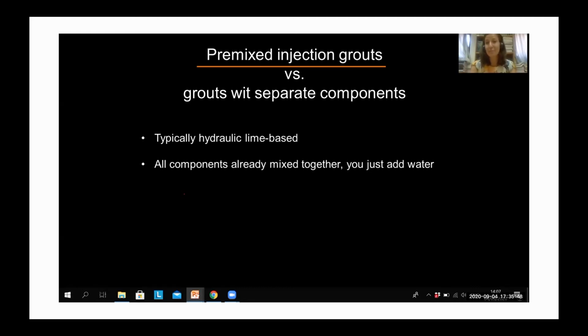how do you find them? They're basically a powder in which all components are already mixed together, and you just need to add water to it. So it's very easy and therefore very tempting to use because it's quick, and it's already tested by the manufacturer. And very often there is presence of additives. I would say in all premixed grouts there is presence of additives. So there are, for example, air entrainers, and plasticizers very often to make it very injectable. So that sounds all very appealing and easy and good to do.